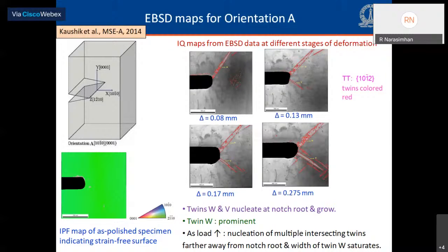On the bottom left side, we see the inverse pole figure map of the as polished specimen. And we can see a strain-free surface in this case. The right side sequence of images are image quality maps obtained from the EBSD data corresponding to different stages of deformation, load point displacements delta. And here the extension twins, the TTs, are colored red, the 101 bar 2 twins.